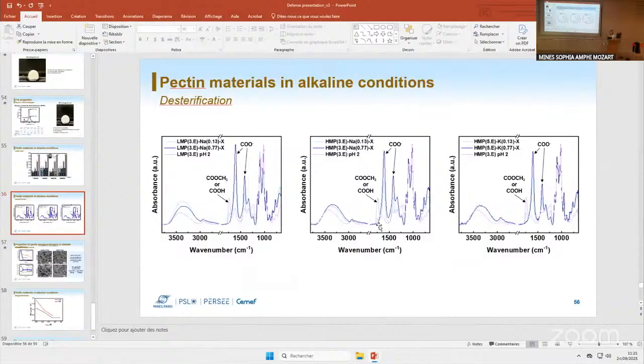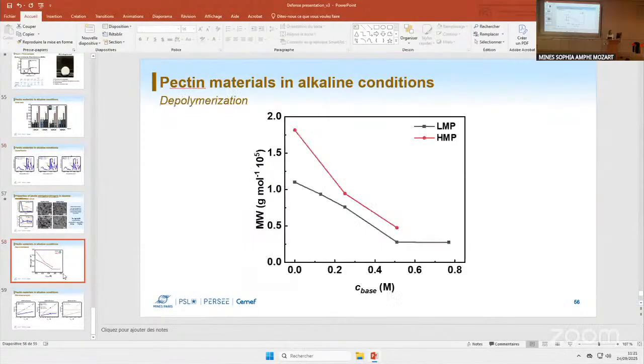deesterifying the pectin chains. And in terms of molecular weight, we saw how it changes because we expected it to change a lot. We saw that we're reducing a lot, but we're not very far from high and low methoxy pectin. So after the base has acted in the system and is mixed, we consider that the chains in there are similar. So I would not say that the degree of esterification or the molecular weight have any effect.